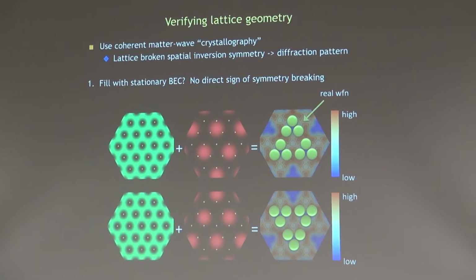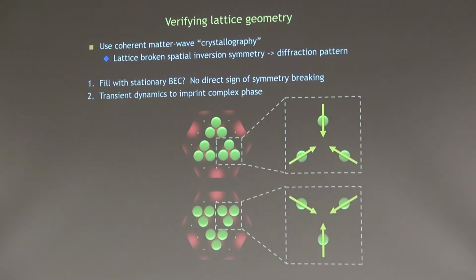Okay, so we decided to do something different, which is to load atoms inside of this trimerized Kagome lattice, and then just convert the lattice back to this purely infrared lattice, which we do just by switching off the green light. That's very easy for us to do. And now we have a way of imprinting complex phases into the wave function that should reveal the spatial asymmetry of the lattice.